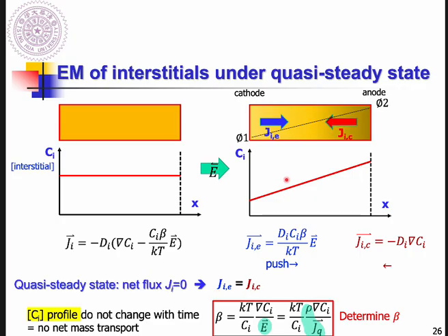you can choose 3 different time points, do a sectioning and analysis to plot this concentration profile, to check whether the concentration profile changes with time or not.